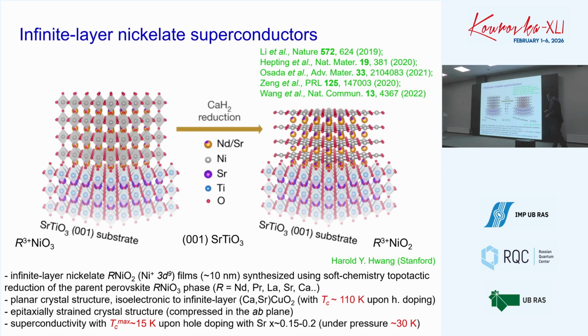As I said, this real breakthrough was made in the group of Harold Hwang in Stanford very recently, some 6 or 7 years ago. It's some kind of complex chemistry. They tried to synthesize these infinite layer systems because they are isoelectronic and isostructural to infinite layer cuprates, which show quite a strong TC of about 100 K upon hole doping. That's why people claimed that if you were able to synthesize these materials, then they would probably be superconducting. It took, I think, decades to be able to synthesize clean infinite layer systems.